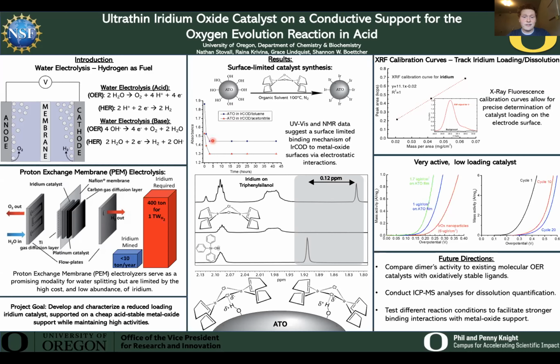After about 2.5 hours, as you can see, this absorbance plateaued in both toluene and acetonitrile. This suggests that our reaction is surface limited, likely by the surface hydroxyl groups of ATO.